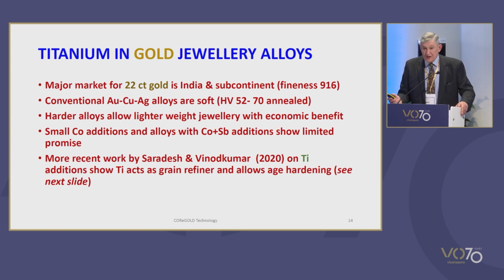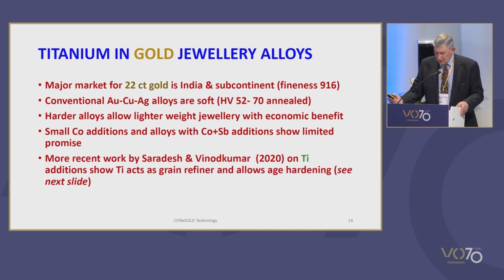A major market for gold jewellery is 22 carat gold in the Indian subcontinent. With a fineness of 916, such 22 carat gold alloys are soft with hardnesses of about 52 to 70 Vickers in the annealed condition. Use of a much harder 22 carat gold alloy would allow lighter weight jewellery with economic benefit. The use of small cobalt additions and conventional alloying with cobalt plus antimony additions show some promise.